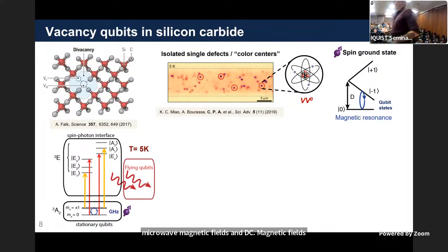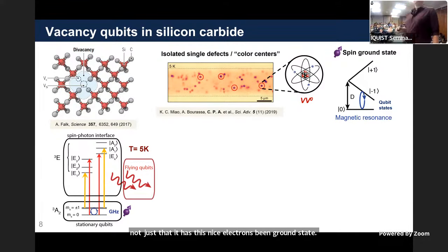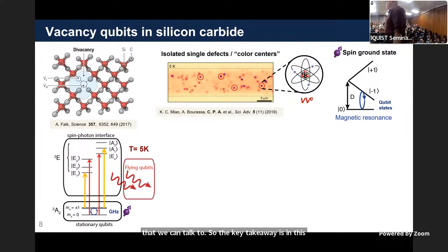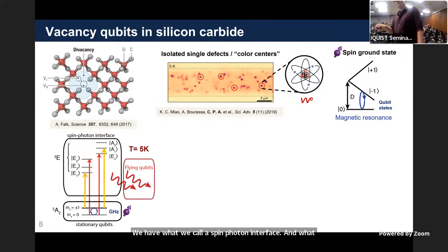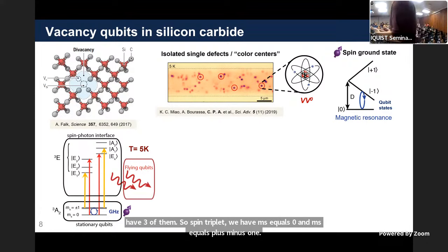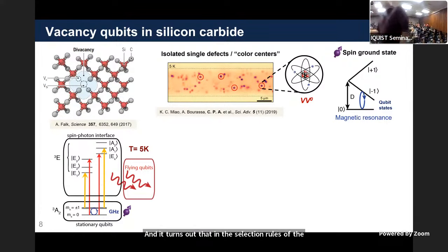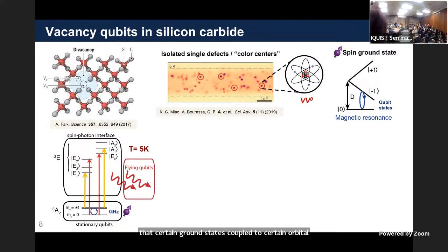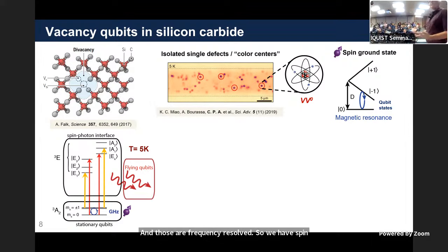But the thing that we really like about the system is not just that it has this nice electron spin ground state, but that it has this interface to light, these orbitals that we can talk to. So the key takeaway is that in this particular system, we have what we call a spin-photon interface. And what that simply means is that we have our ground states. We have three of them. It's a spin triplet. We have m_s equals zero and m_s equals plus/minus one. And it turns out that in the selection rules of the system, just like there are selection rules in an atom, certain ground states couple to certain orbital states and other ground states couple to a different set of orbital states. And those are frequency resolved.